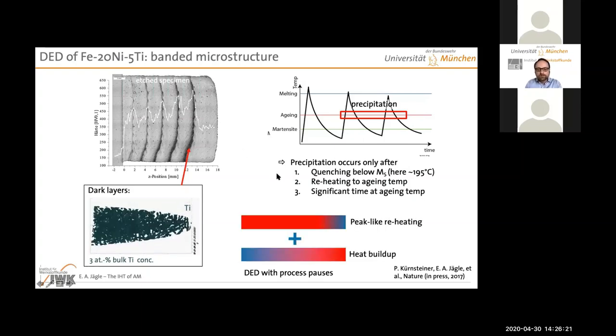Okay, so basically, if we go back to our cartoons here, you have a combination of 2 things: peak-like reheating, but also this slight increase overall, which is probably due to the overall heat input in the sample as you deposit. So that's why you have not only zigzag in the zebra stripes, but you also have this overall increase.